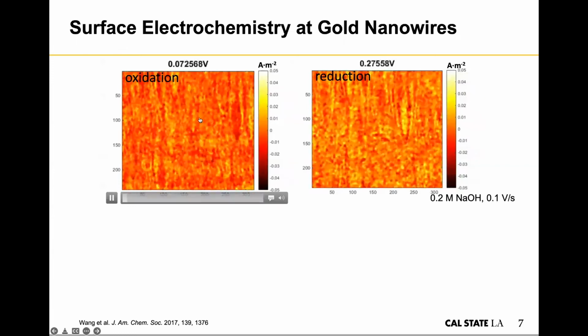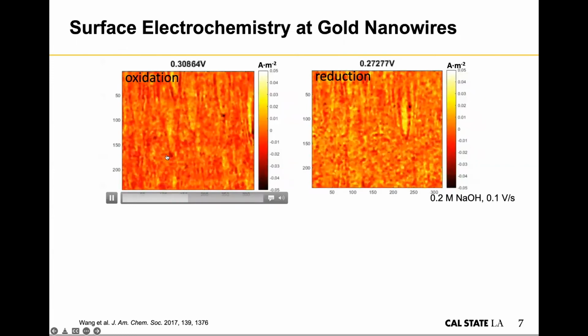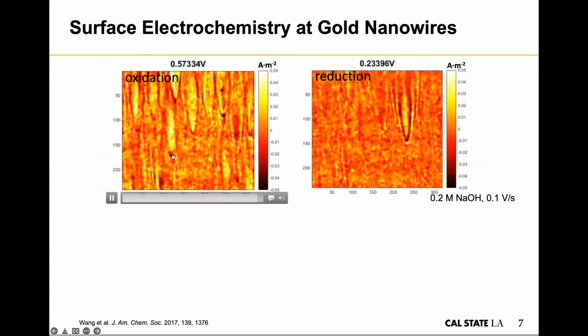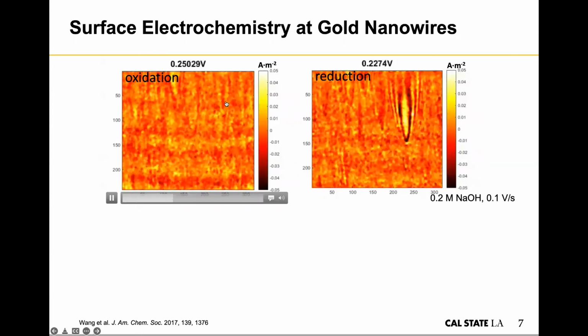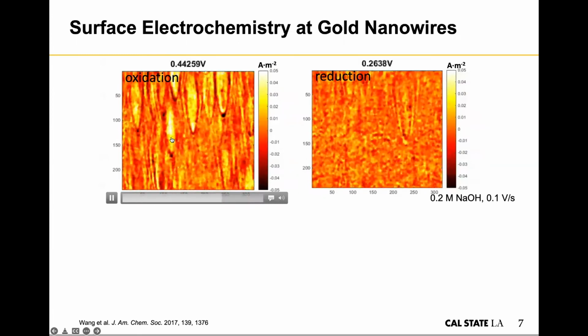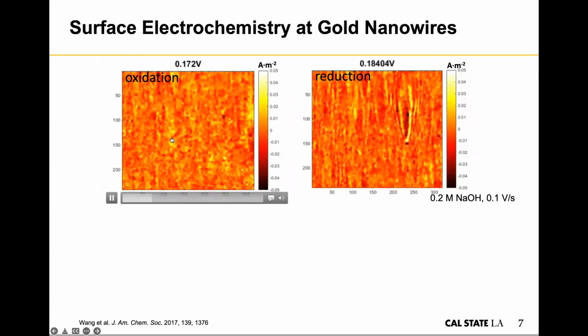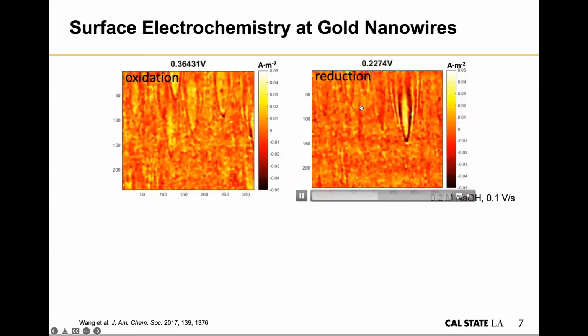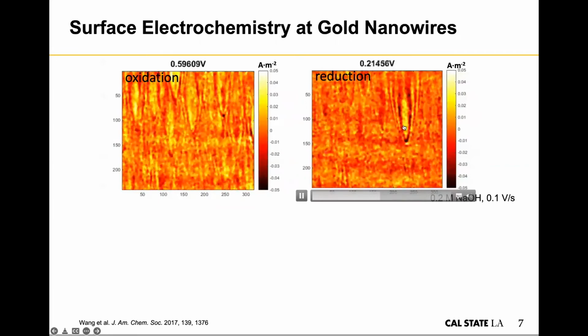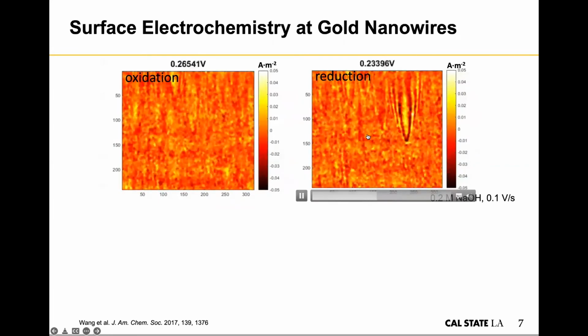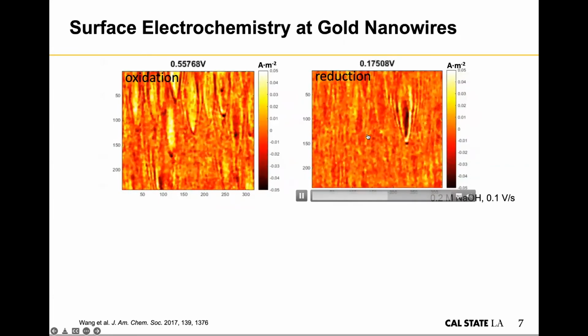So you can see that each tail represents a gold nanowire. The wire is sitting at the top of the tail. And you can see that when the oxidation is going on, the intensity increases. And then this is during the reduction. It's an opposite signal compared to the oxidation.